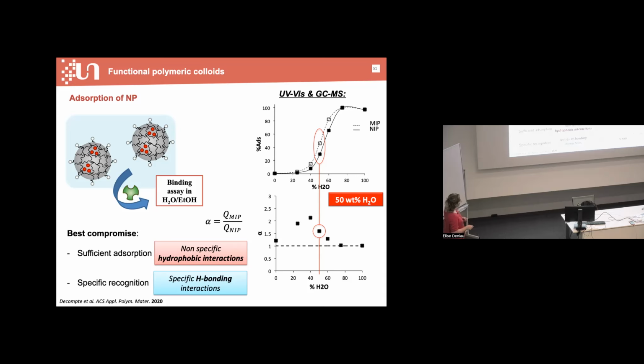The higher specificity was found here for 40% of water in ethanol. But if you check, the adsorption yield is rather low. So the best compromise was found for 50% of water in ethanol, where we have sufficient adsorption and specific recognition.